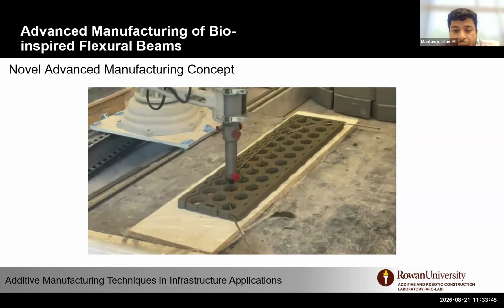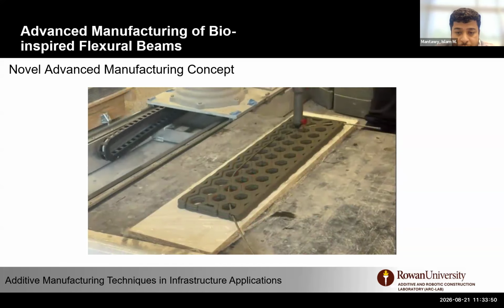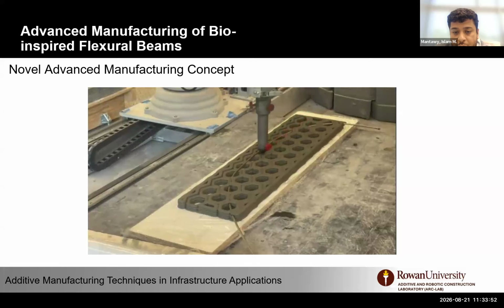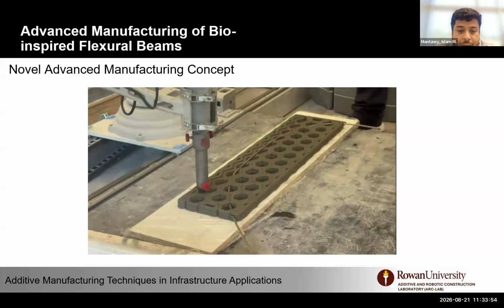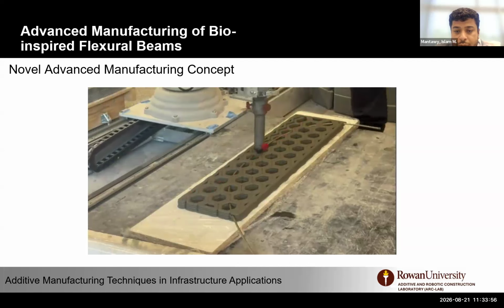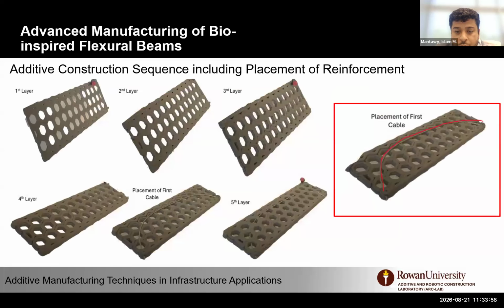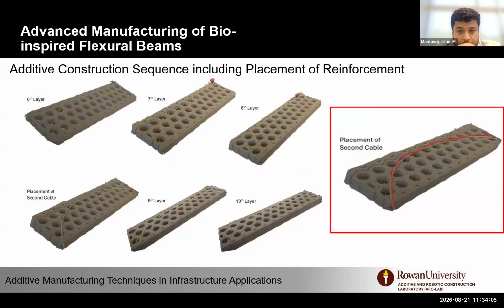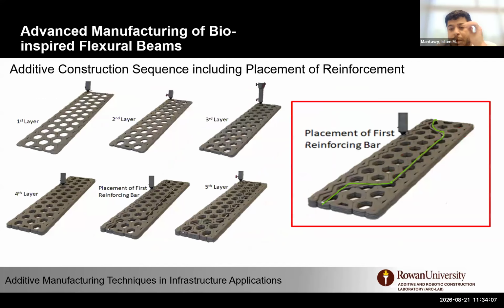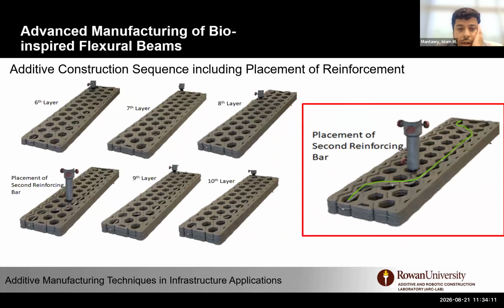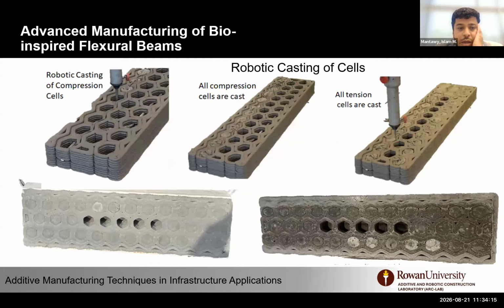In a larger, bigger beam, you will have more benefit of this technology. However, in a smaller one, we may have really just a few cells that are open, that are low stress regions. So as you can see here, we start layer by layer and incorporate reinforcement until we finish. We can also use bent bar and straight bar, and I'm going to explain that in a minute. And the idea later on is, after you finish, to immediately fill those cavities.